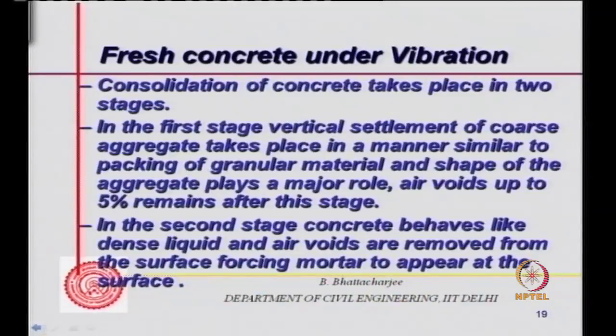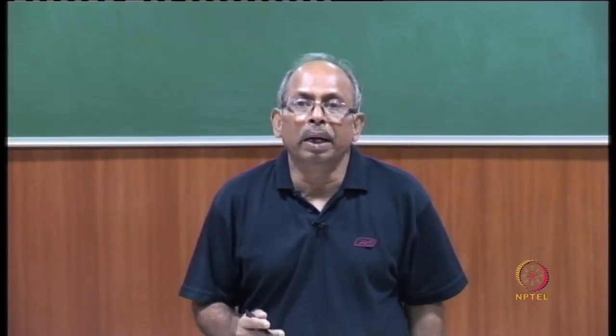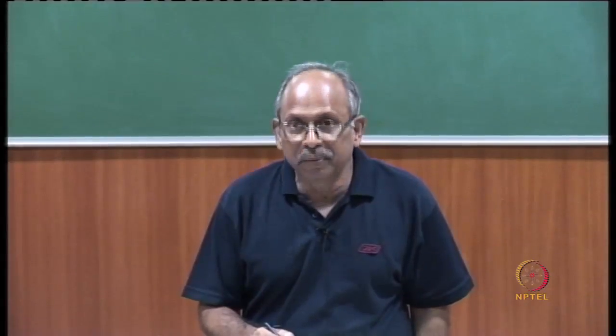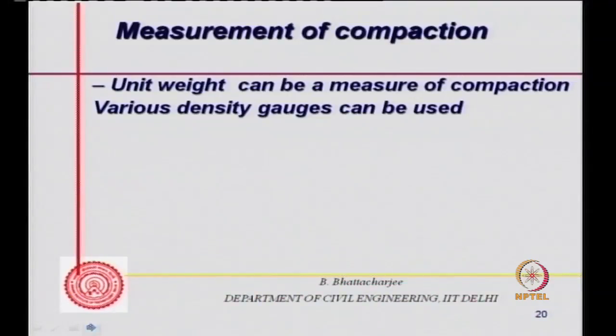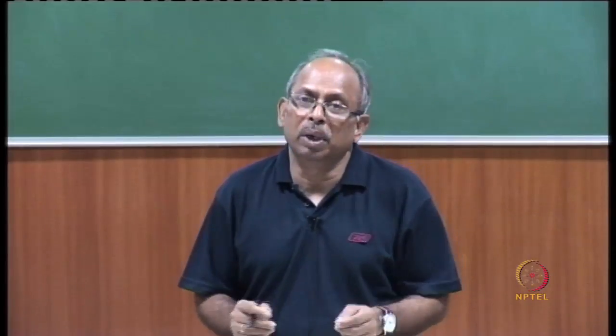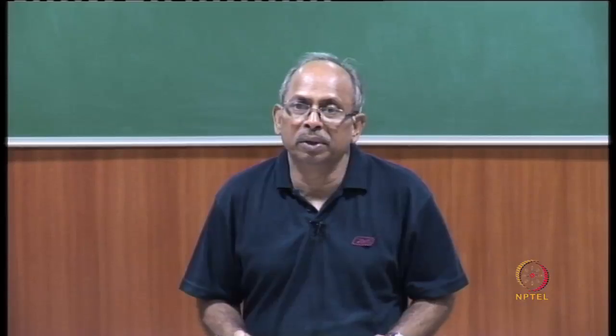This is important to understand, that once the air voids have moved out, the mortar will appear at the surface. So once the first phase is over, in the second phase mortar will come out, and that's also a test for whether the vibration is complete or not. You'll find that the slurry or mortar phase is coming out at the top, and then you can stop vibration.